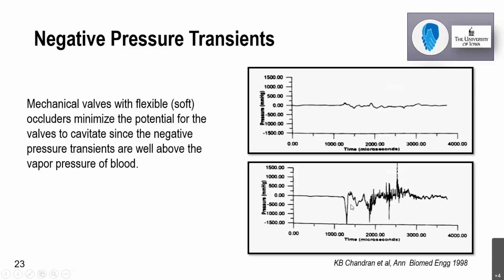negative pressures of the tune of minus 1500 millimeter of mercury can instantaneously form at the distal or the outflow side of the device. But of course, this particular negative pressure lasts for a few microseconds only, but that is good enough to generate the vapor bubbles and collapse of these bubbles.